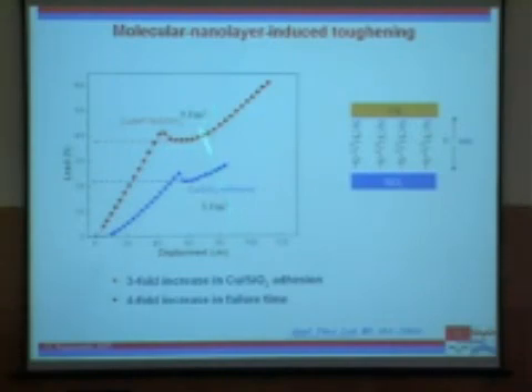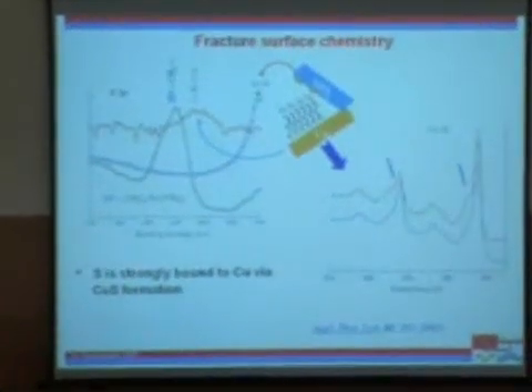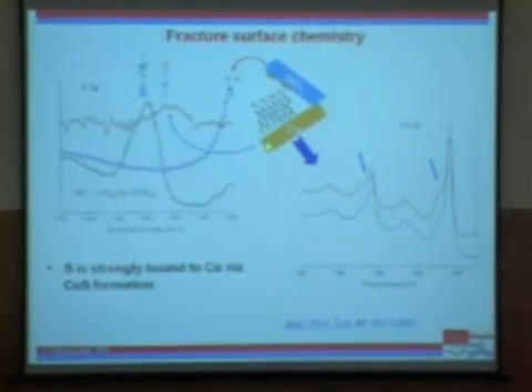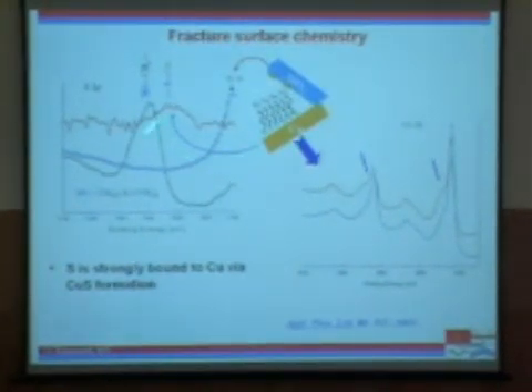And to tell you what these numbers mean, in an Intel chip, I don't know, in a Pentium chip maybe, I don't know what the latest chip is called, but typically for an interface to be considered stable in the chip, the value that you need to meet is about 5 joules per meter squared. So without optimizing and using a single layer, we have actually tripled the value, right? So that is not all. And we know why this is happening. I won't go into the gory details of the spectroscopy studies that we did, but let me just mention that copper and sulfur bond. That bond is shown by spectroscopic signatures over here, and the breakage actually occurs on the silica side of the interface.